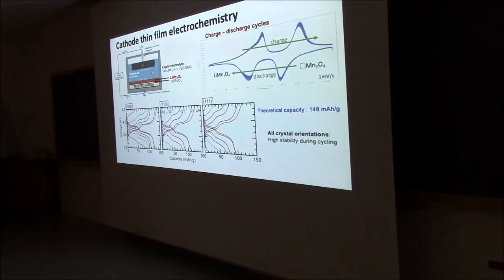Like, for example, if we somehow manage to adjust the texture of this interface between substrate and the deposited, is it possible to move this to lower or higher voltage? No, so the voltage at which this is happening is where the reaction will happen within the structure. The thing you can move is, let's say, where you have top and bottom. If they come further apart from each other, you have more internal resistance, which is a bad thing, so that's what you want to optimize. You want to have them as close as possible. But you cannot move this at once.